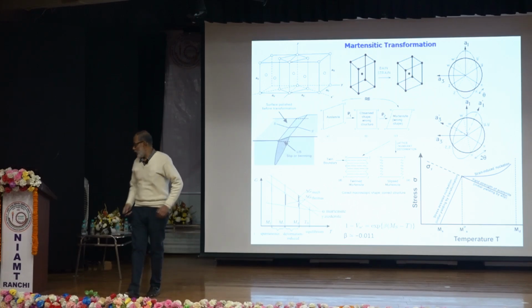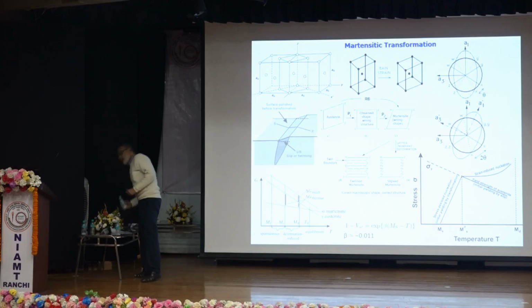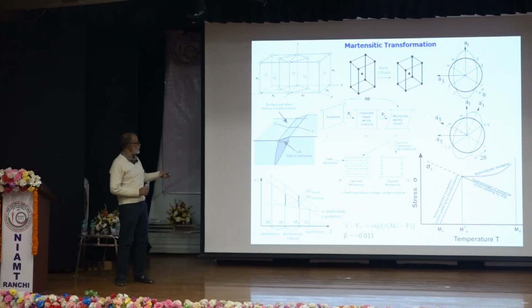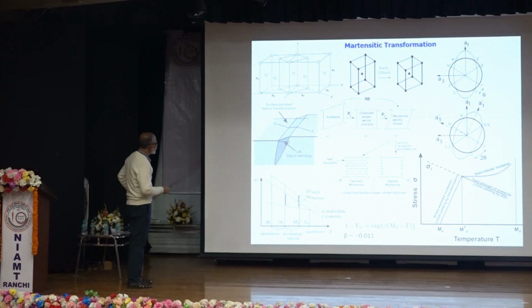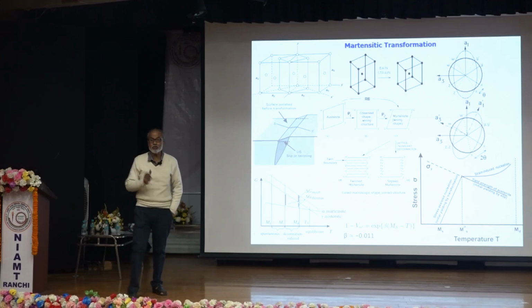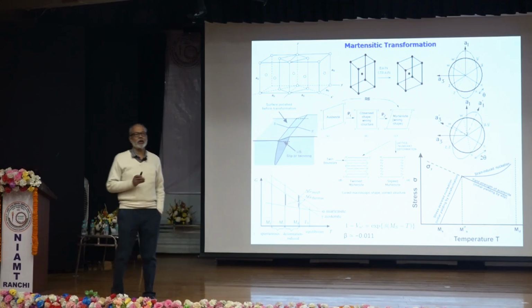So the Bain model was not sufficient to describe the martensitic transformation, as it was found to happen with an invariant plane strain. That is, there has to be an invariant plane. What is an invariant plane? You can conceive, you draw a dotted line over here, create a plane. This plane separates martensite and austenite, and there will be no distortion, no rotation in this plane. And when you move ahead within the martensite from this plane, the strain will increase with distance. So this is the character of an invariant plane. So we need to have a phenomenology which can justify the occurrence of an invariant plane.